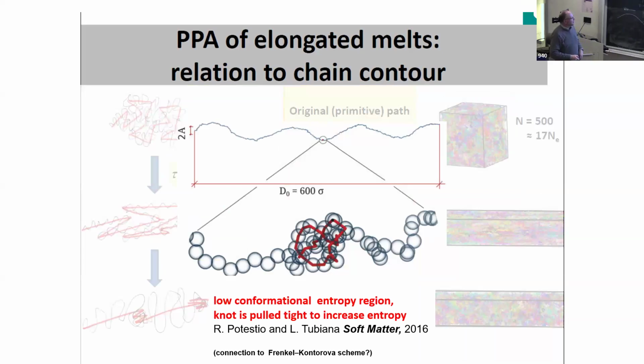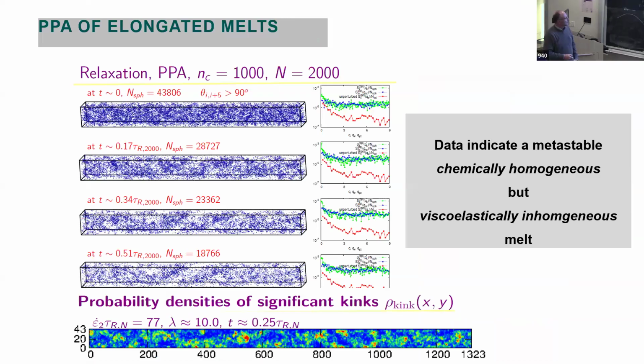And this reminds very much of this situation here again, because again, we have a system which is under tension, and we have knots between the chains, and it looks like we get a very similar situation as in this single chain simulation. And we can analyze this. You see here congestions of close links between different chains, which then survive for a very long time. That's for an extension of a factor of 5, that's a factor of 10, and you see similar pictures.